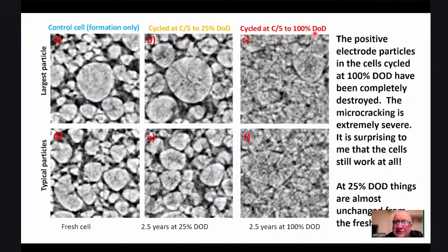But after cycling at 100% depth of discharge for 2.5 years, you can see the particles have just completely been destroyed by this microcracking. It's extremely severe. And this is because the volume changes of the lattice constants are bigger when you undergo the 100% depth of discharge. You have bigger volume changes all the time, and that causes this microcracking. So it's kind of a surprise that these cells cycled at 100% depth of discharge even work, but they still work reasonably well. And this is, again, another reason why these shallow discharge cycles are better if you want to have a longer lifetime.